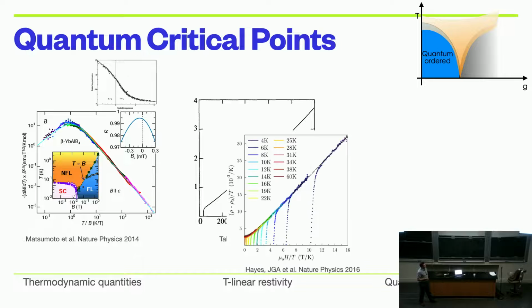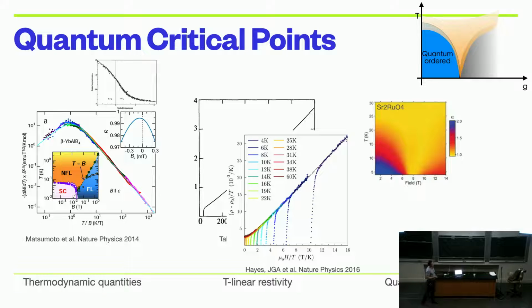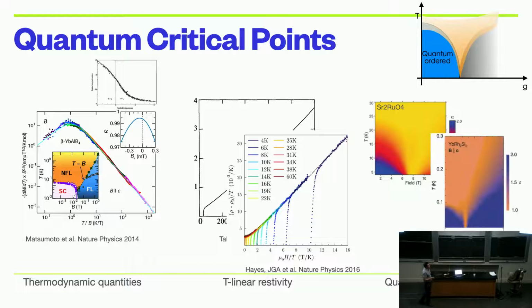Our contribution to this is that we connected the T-linear resistivity to B-linear resistivity, and that's what you see here. So again, some kind of scaling behavior near the critical point. And then lots and lots of these colorful phase diagrams. So people put together, in this case for this material, strontium ruthenate, this is the power law associated with the resistivity across a critical point, and it looks like it really is an energy scale that's vanishing and leading to this strongly T-linear behavior in the center.